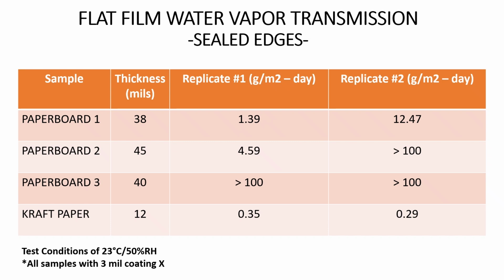So what was found was that there were pinholes present in half of the measurements that were done, which saturated the detector. That's why you have greater than 100, because it actually saturated the detector to where it could not read any more water vapor. And they also noticed that different labs are giving different results, because some labs were testing by covering the edges where others were not. Some labs had different ambient relative humidity in them, and that also skewed the results.